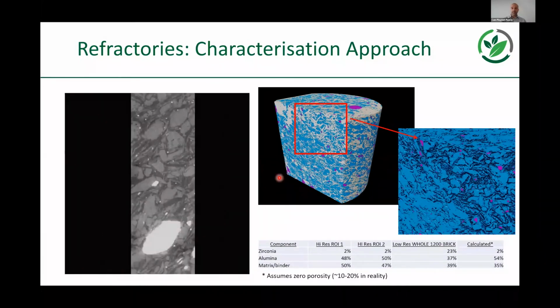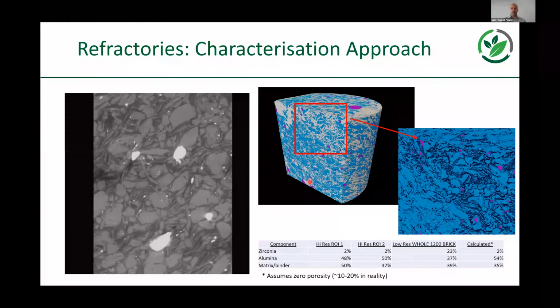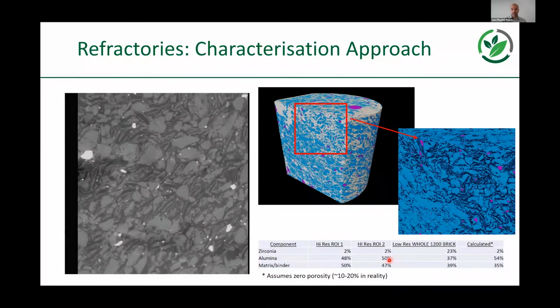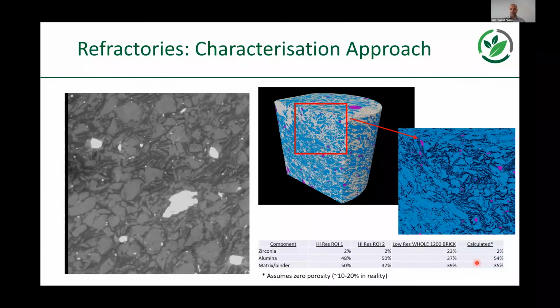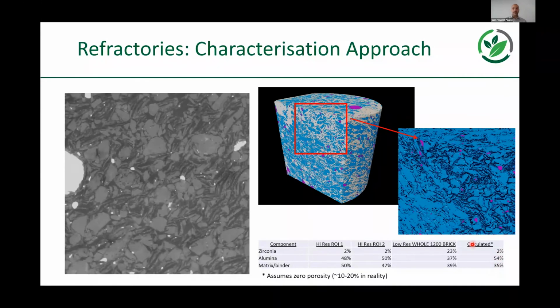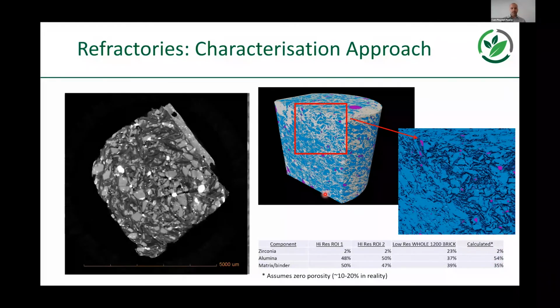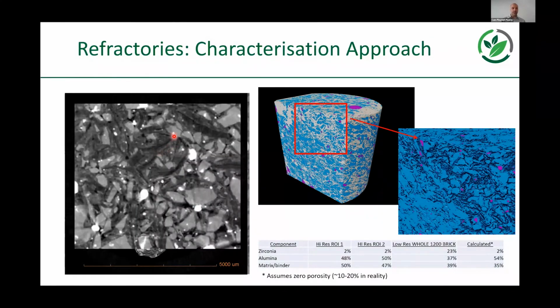And then what we can do is look at how we segment those different components, and through quite a long series of optimizations, we've been able to get pretty close, once you account for the porosity, to the calculated values that we have there. But one of the problems that we have, to acknowledge that and be honest about it, is that whilst we can see the binder, the detail of what is happening inside that binder, i.e. the difference between the way that the graphite is behaving and the resin behaves, is much more difficult to define. So we can see this with our eyes, but getting the computers to see that and digitally segment that is becoming more challenging. So we need to look at a range of other techniques that we can use to help us visualize that and understand how that component of the refractory is behaving.